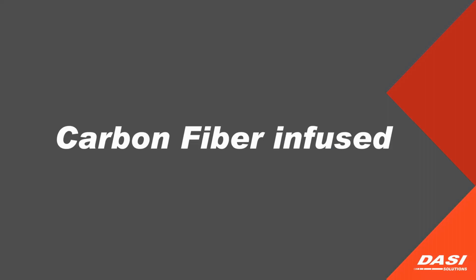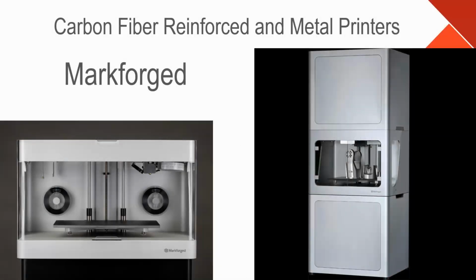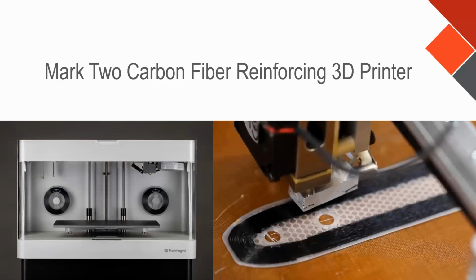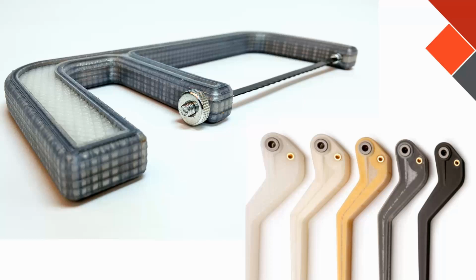Now, carbon fiber infused, as well as metal printers, are really becoming more and more popular and less expensive as a result of their popularity these days. When you're dealing with carbon fiber printers, these are adding layers based on a bit of a vetting or simulation that their software does. And based on the way the part's going to be used, it will strategically layer the strands of carbon fiber between the layers of more traditional FDM type printing. So it's a fantastic tool. Now it creates very good end-use products. It can shrink the size due to the improved strength, or it can just create an unmanufacturable but strength necessary type of a part that can be used simply as the end product.